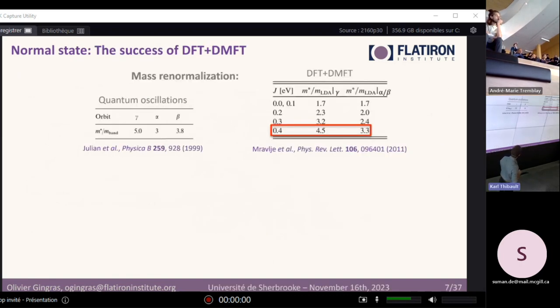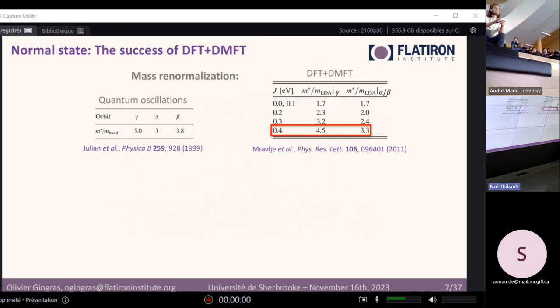Okay, so DFT plus DMFT in the context of strontium ruthenate has been very successful. One of the key things that highlights this fact is the mass renormalization. It's standard in correlated systems that the mass of the electrons that you would obtain from DFT is underestimated because it's lacking electronic correlations. If you look at the renormalization compared to DFT from quantum oscillation, you see that the numbers are pretty large, so it's an intermediate to strongly correlated system. And the masses depend on the different Fermi surfaces of the material. This is beautifully reproduced within the DFT plus DMFT calculation, where it was shown that the Hund's coupling, which favors same spin alignment, leads to this differentiation between the different bands, the different effective masses, and leads to the correct order of magnitude of the value of the mass.